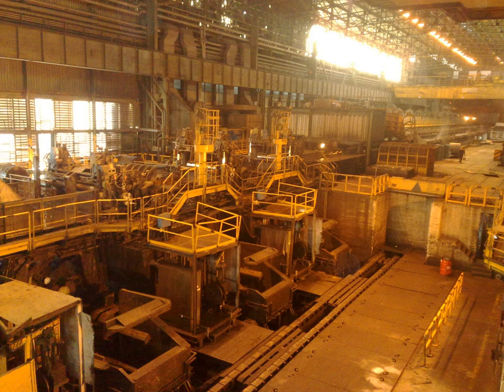Additionally, there are 4 continuous slab casting machines, each having 2 arc casting strands, radius 10.5 meters. They produce the plant's final product, called slabs. These slabs are 10 meters long, 20 centimeters in thickness, and 65 to 188 centimeters adjustable width. Slab production capacity is 4,200,000 t per year, revamping year 2000, to be increased in steps to 5,400,000 and 7,200,000 mtpy. Slabs are manually cooled and scarfed in the slab cooling and conditioning plant.